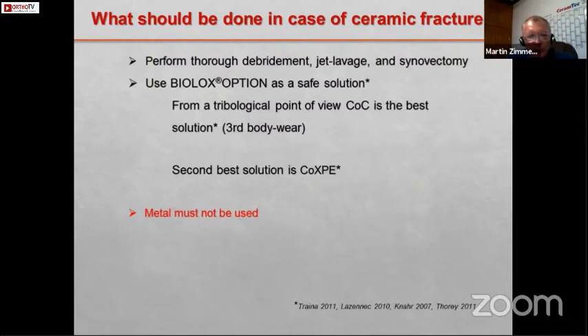From a tribological point of view, the best situation is to use ceramic on ceramic, because then these remaining ceramic particles will not affect the articulation and the wear issue. And the second best solution is to have ceramic on highly cross-linked polyethylene. We also have some cases that we can show where the ceramic particles, which still remain in vivo in the articulation, become embedded in the polyethylene, but do not affect the scratch surface and the scratch resistance of the ceramic. So again, and that's maybe the most important slide here, speaking about the BIOLOX OPTION after revision of a fracture of a ceramic, never use a metallic ball head as a replacement.